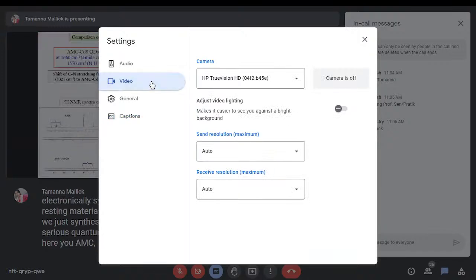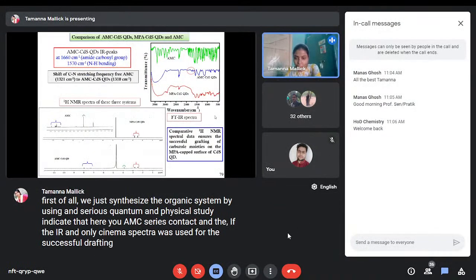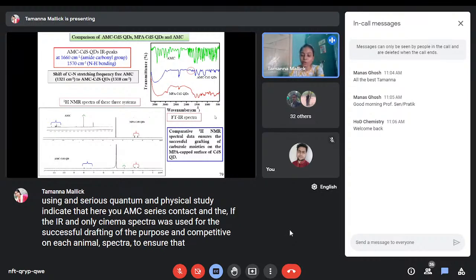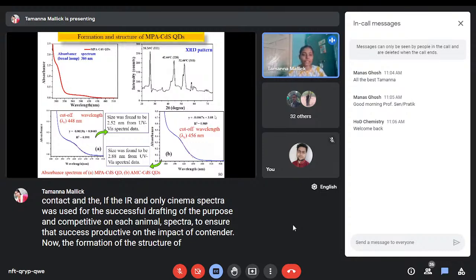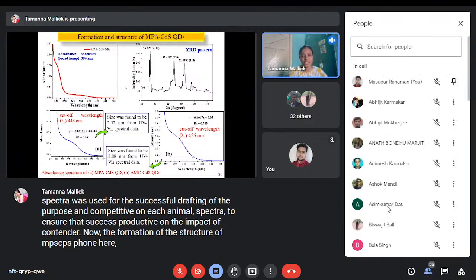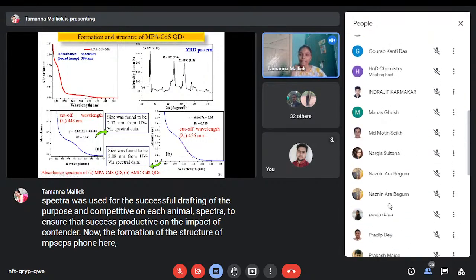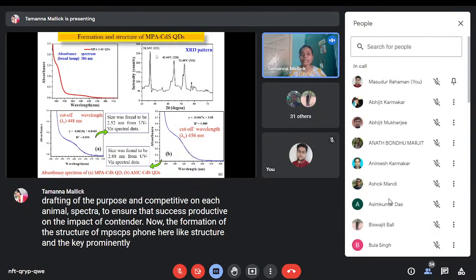This is the synthesis procedure of the AMC CdS quantum dot. FTIR and proton NMR spectra were used to confirm the successful grafting of the carbazole on the quantum dot surface, and comparative proton NMR spectra ensured the successful grafting of the carbazole moiety on the MPA capped surface of the quantum dot. Now, the formation and structure of MPA CdS quantum dots are shown here using absorption spectroscopy. A broad hump at 386 nanometer was observed in the case of MPA CdS quantum dot, and the powder XRD data clearly indicate three prominent peaks, closely resembling a zinc blende-like structure. The three prominent peaks indicate the 111, 220, and 311 planes. And the size